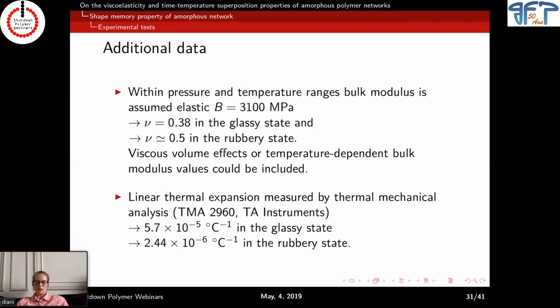And we had two approaches. First, we did a measure in the glassy state and in the rubbery state. But then if we had to do the whole history and have good stress in uniaxial tension, we needed to measure it and give the whole history as a function of the temperature rate, because you know the linear expansion also depends on the temperature rate.